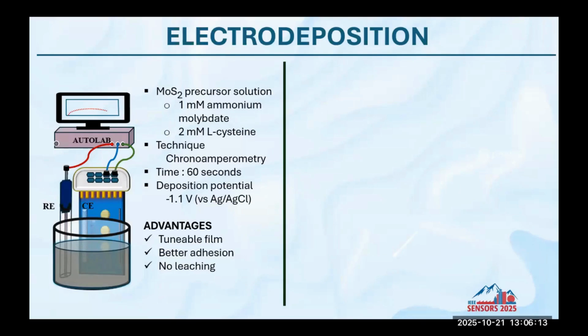And we are preparing a solution and running a chrono-amperometric setup where we are applying a negative potential of minus 1.1 volts for 60 seconds, where the ammonium molybdate and L-cysteine react in a mildly acidic solution to form a layer on the electrode fingers. The advantage of electrodepositing is that we do not face the leaching challenge.